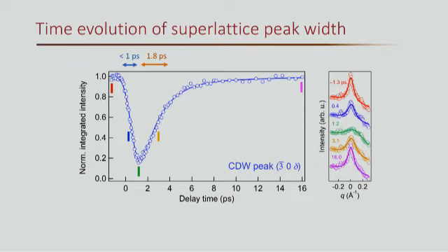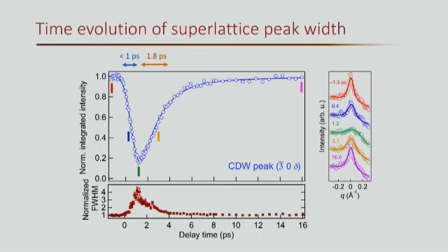We can, of course, also fit all the peaks as a function of time. This is the full width at half maximum from the fitting, plotted as a function of time, where we see two features. One is that the peak got broadened. And second, the recovery of the peak width is in line with the recovery of the intensity itself. So what does broadening mean? Loosely speaking, broadening of the peak tells you there's a loss of long-range coherence. From a cartoon picture point of view, if this is the entire domain of the CDW order parameter before the pump excitation, a loss of long-range coherence means they're creating a lot of different small domains of fluctuating charge density wave as we pump and suppress the CDW intensity.